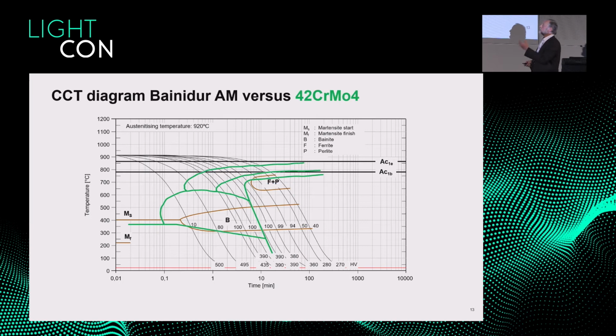Here's the comparison of this development. We have a very broad range of cooling rates to form completely bainite. The green lines is the same CCT diagram for 42CrMo4, and we claim we have the longest nose in the steel industry regarding the bainite transformation, because this looks like a nose.